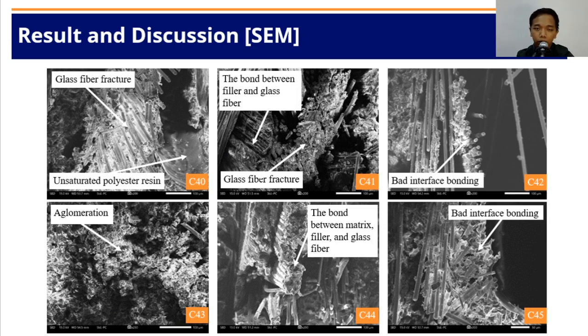The composite C41 shows a good interfacial bond between the glass fiber, matrix, and filler. This is in line with the result of the impact test that C41 has the best impact strength among the other filled specimens. The composite C43 has the lowest impact result among the other specimens. As we can see in this picture, it has been observed that in C43 composite, there are areas of filler agglomeration that cause a decrease in the impact strength of the specimen.